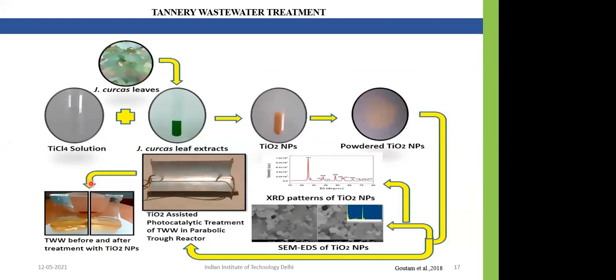So these titanium dioxide nanoparticles were synthesized using leaf extract of the Jatropha plant, and the precursor salt was titanium chloride. Moreover, the green synthesized TiO2 nanoparticles were further characterized by UV-visible spectrophotometer and FTIR measurement, and even XRD was employed for the characterization of the synthesized nanoparticles. So the results of this study confirm the synthesis and the anatase phase of the spherical TiO2 nanoparticles, and also unfold the presence of phytochemicals in the leaf extract, which might be involved in the capping or stabilization of nanoparticles.